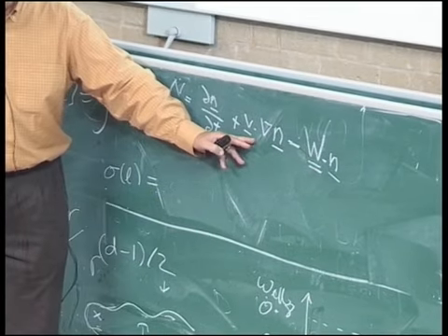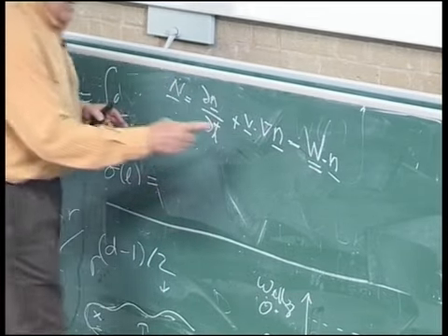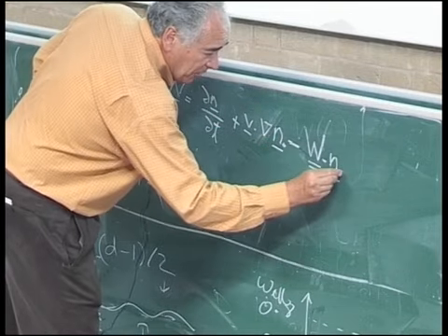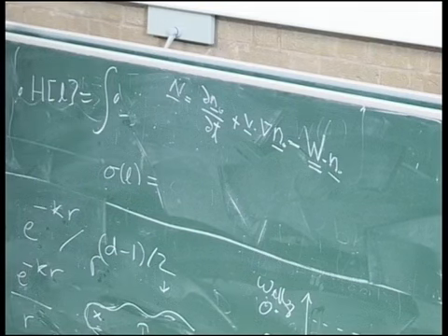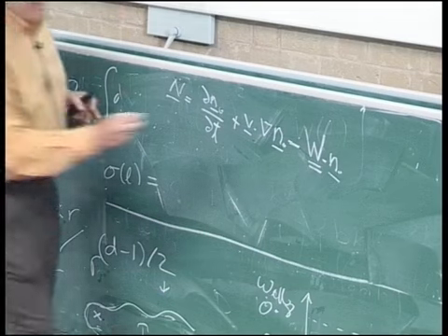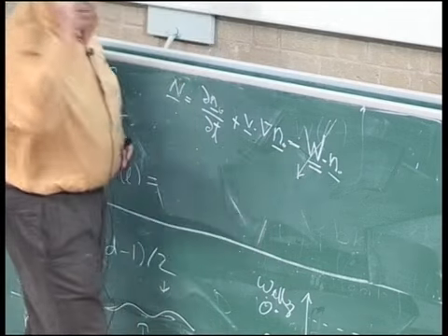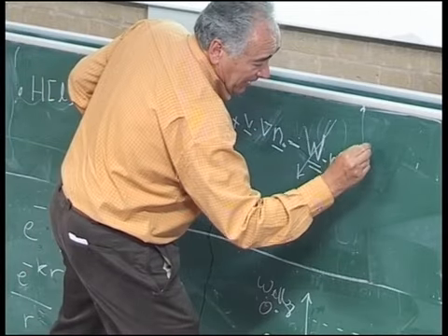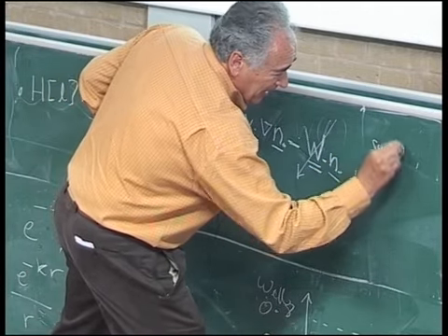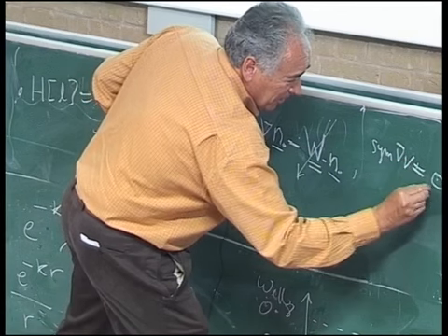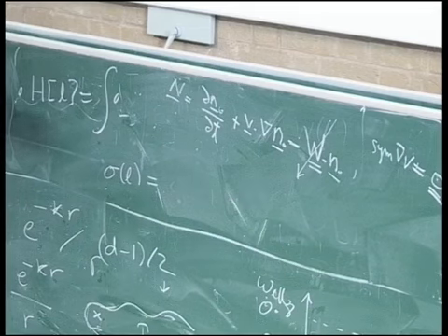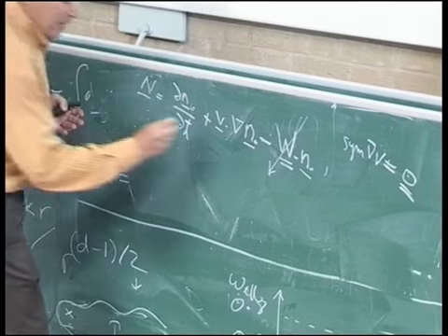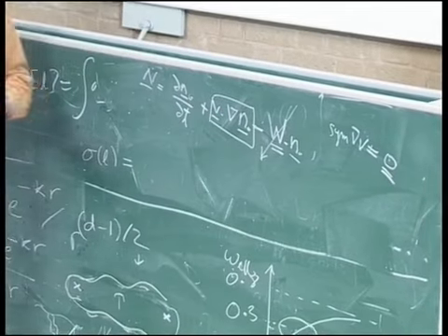And this is the convective part. And n, I will put n0. N0 is the director orientation that describes this helix. Because this is plug flow, this is 0. The symmetric part of the velocity gradient is also 0. Everything is 0. The only thing that contributes to this dissipation is this term.